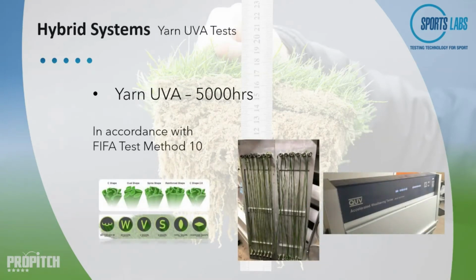Each yarn shape and colour require testing for UVA, and there are many yarn shapes and shades of green, some of which you can see here. The yarns are loaded into the UV cabinet, as you can see in the plate in the centre, and they're subjected to repeated cycles of UV and condensation, with the 5,000 hours of UV exposure taking up to 7 months to complete.